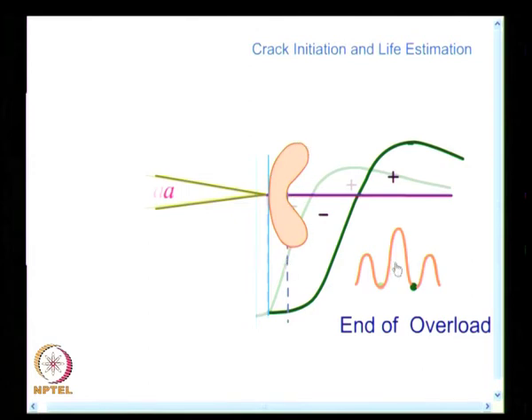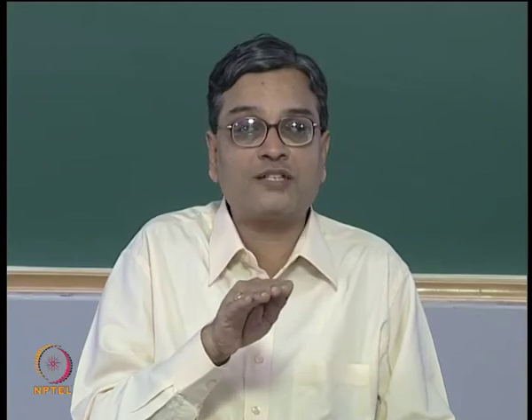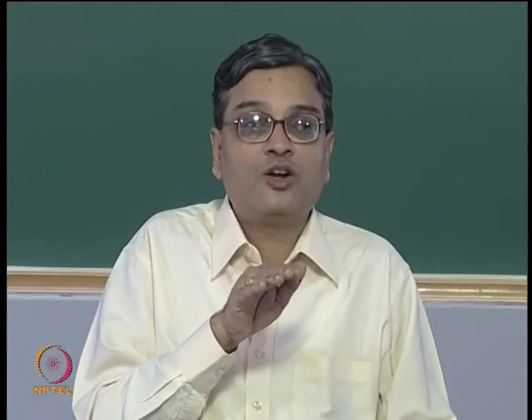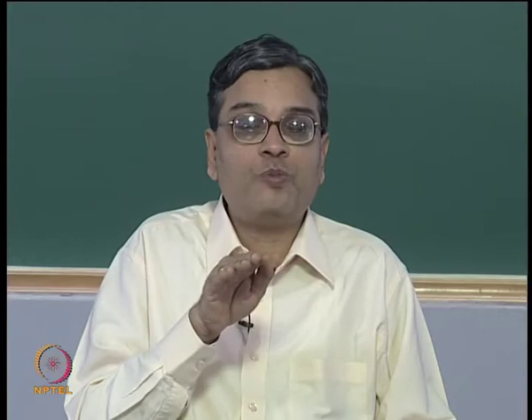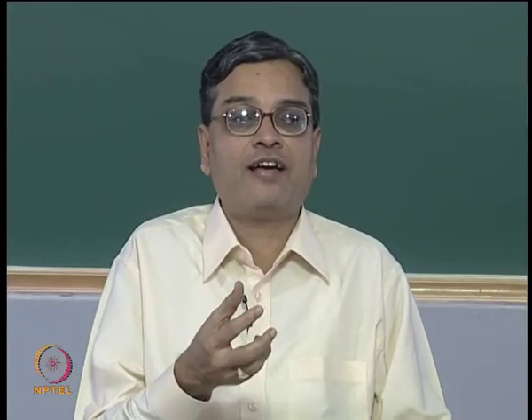So, after an overload, you have only a smaller load that is coming in the actual loading situation. So, the smaller load will introduce only a small sized plastic zone, but this plastic zone will remain within the overload plastic zone. So, as long as the crack remains within the overload plastic zone, the growth rate of the crack would be retarded, and you also need to have some kind of a quantitative estimation.